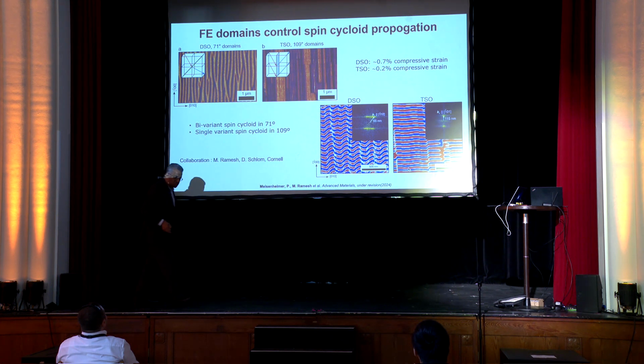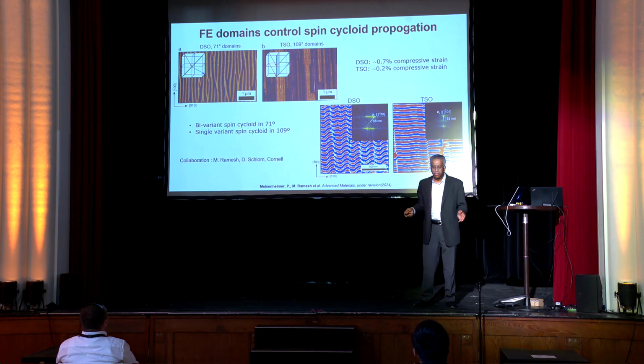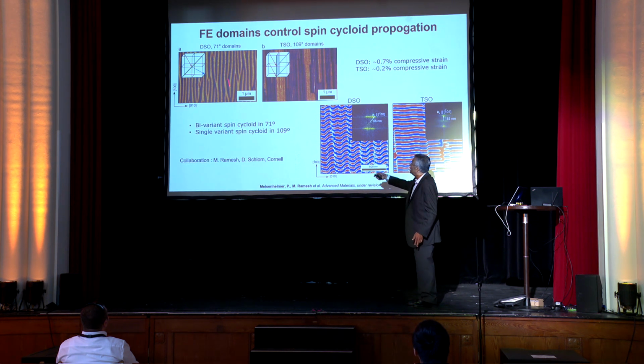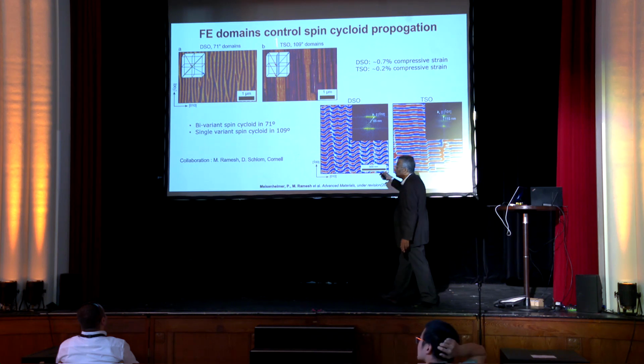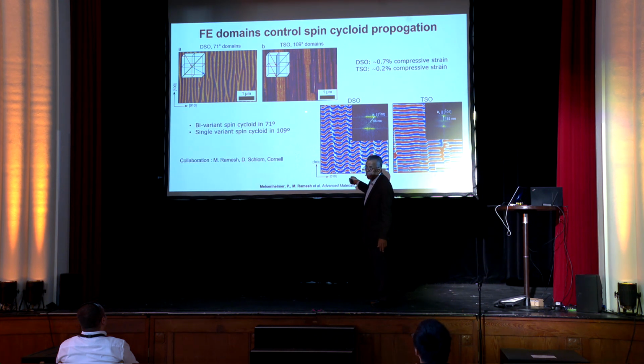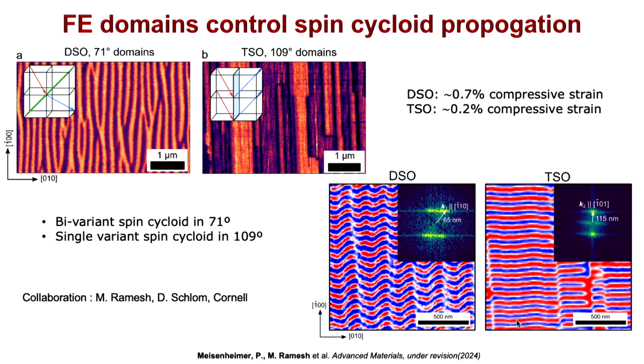Now, if you grow bismuth ferrite on dysprosium scandate, which is about 0.8% mismatched to the bismuth ferrite, you start to see this very nice ferroelastic twin-like structure. We call them 71-degree domains. If I go to a sister substrate, terbium scandate, which is only 0.1% mismatched, you start to see not 71, but 109-degree domains. Mainly because electrostatics dominates here, while elastic energy dominates here.